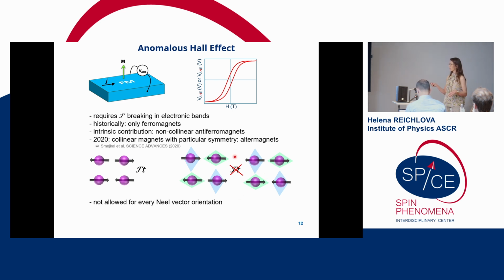So therefore the time-reversal symmetry is not a symmetry, and based on Libor's prediction here, we do expect that the anomalous Hall effect is allowed in these altermagnetic materials. What is important to note is that unlike in ferromagnets, where we always have an allowed anomalous Hall effect, in altermagnets it naturally depends on the orientation of the Néel vector whether the time-reversal symmetry is broken or not, and therefore it can be highly anisotropic.